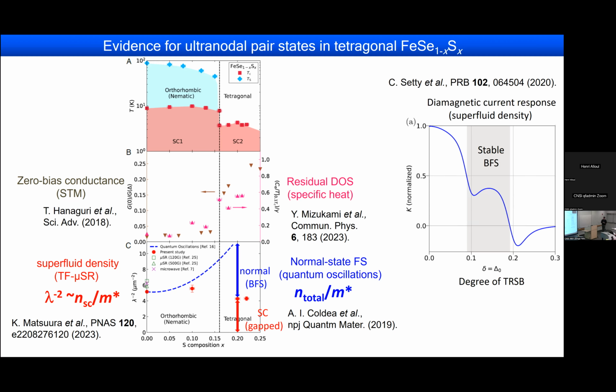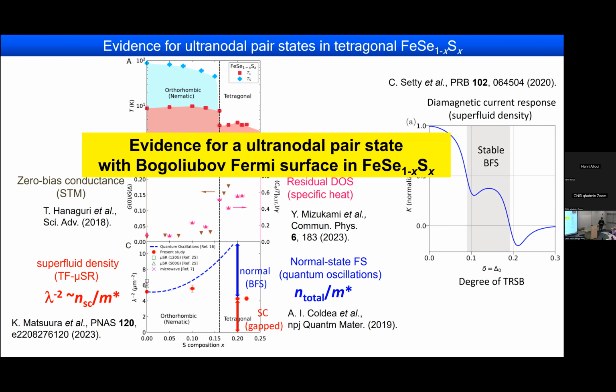Okay, and a recent calculation by Peter Hirschfeld's group shows that they can estimate the diamagnetic current response or superfluid density as a function of some kind of parameter, and they find the stable Bogoliubov Fermi surface in this hatched area, in which you can find that the superfluid density should be strongly suppressed from the original value. So this seems to be consistent with what we have observed in the μSR results. So from these results, we conclude that we have evidence for the so-called ultranodal pair state with Bogoliubov Fermi surface in iron selenium sulfur in the SC2 phase.